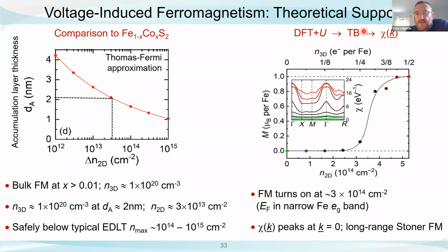And then importantly, we did a tight binding parameterization of that DFT calculated band structure so that we could calculate the electronic susceptibility. And that's shown here in the inset as a function of k, as a function of electron density. And as you go to high electron densities in this system, what is happening is a peak around the gamma point. So it looks like real long-range ordered ferromagnetism. And the point where this emerges is actually exactly where the Fermi level gets to a very narrow iron eg band in the conduction band. At that point, we think that what happens here is we're able to hit the Stoner criterion by accumulation of electron density alone. And that's how we're able to trigger ferromagnetism from a diamagnetic starting point.